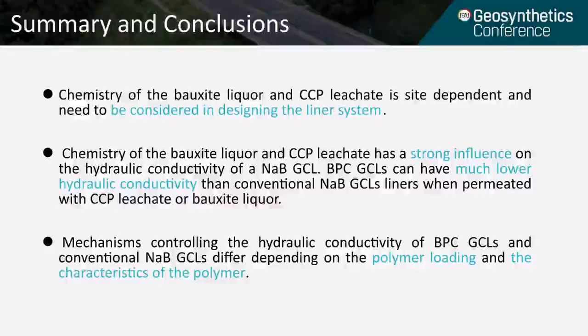This leachate chemistry can strongly influence the hydraulic conductivity of sodium bentonite GCLs. But you will often find BPC GCLs can have much lower hydraulic conductivity than sodium bentonite GCLs, and this should be a good alternative for soil liner or sodium bentonite GCLs. And then the mechanisms controlling hydraulic conductivity for BPC GCLs is different from sodium bentonite GCLs. Usually sodium bentonite GCLs quite depend on the swelling mechanism of swell behavior of the bentonite, while the BPCs highly rely on the polymer, where the polymer loading, the characteristics of polymer can be very important.